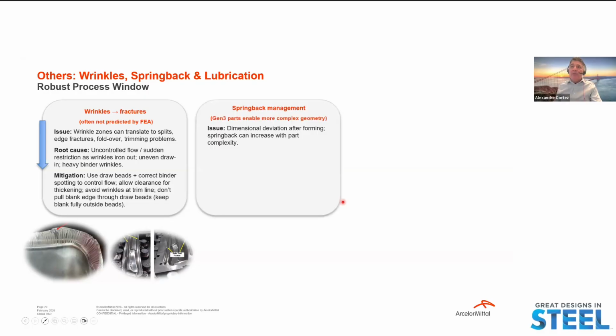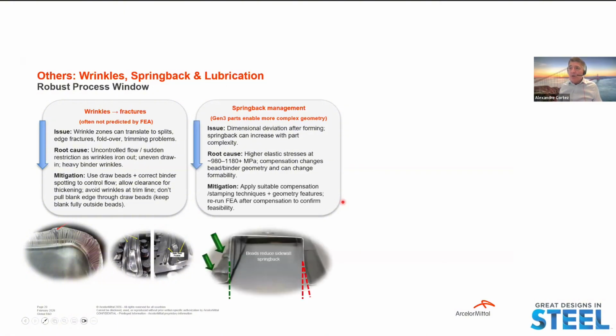Related to spring back management, the issue that we raise is dimension deviation after forming. Spring back can increase with part complexity. The root cause is higher elastic stress at 980 and 1180 and beyond strength levels. Compensation changes bead and binder geometry and can change formability. The mitigation applies suitable compensation, stamping techniques, plus geometry features, and reruns the forming simulation after compensation to confirm feasibility.